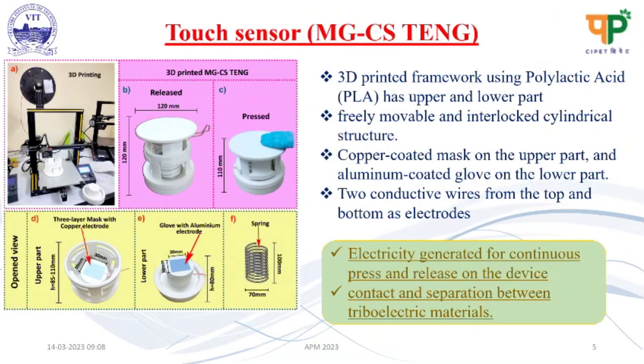Using these three-layer mask and glove, we have fabricated a contact separation triboelectric nanogenerator named MG-CS TENG. For that, a 3D printed framework was made which has an upper and lower part. A piece of copper coated mask was fixed on the upper part, and a piece of aluminum coated glove was fixed on the lower part. These copper and aluminum act as top and bottom electrodes.